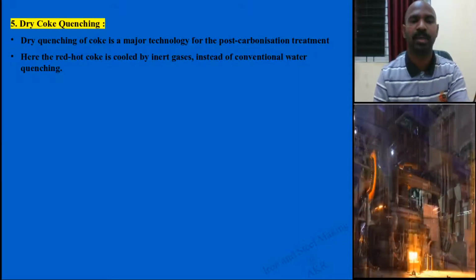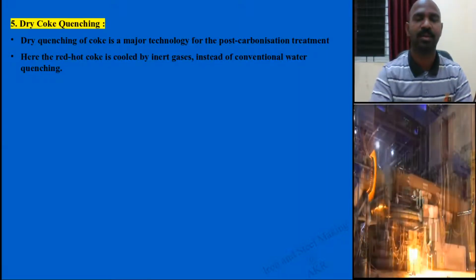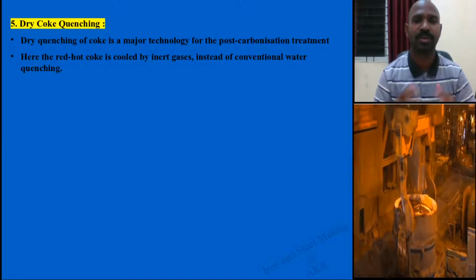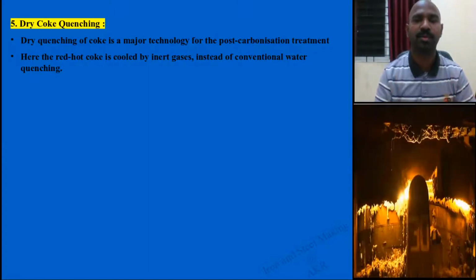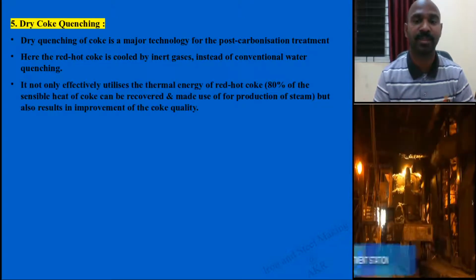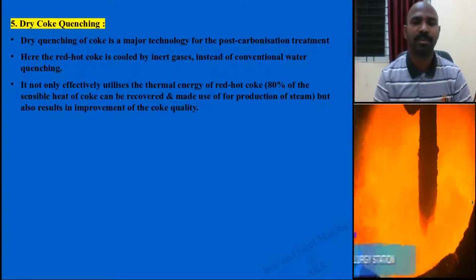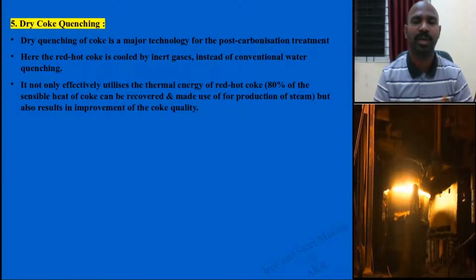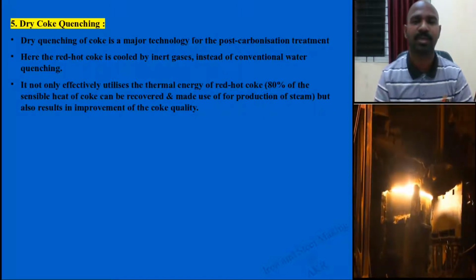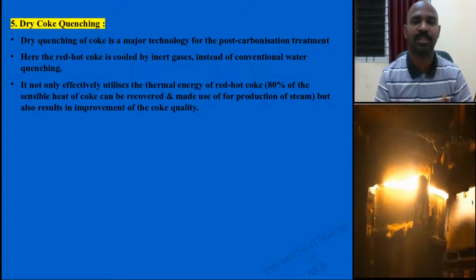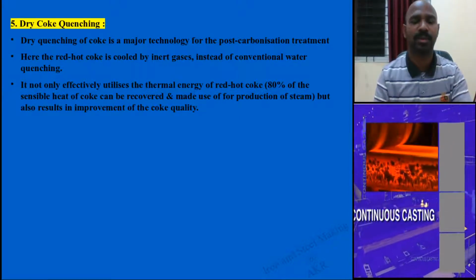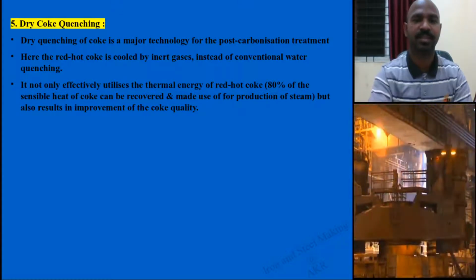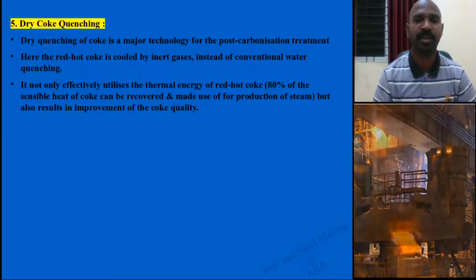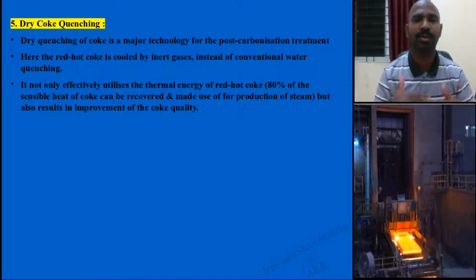Here you use inert gases. The coke is cooled by inert gases instead of water quenching. The red hot coke is taken and inert gases are used to cool it. The advantage of doing this is that not only does it effectively use the red hot thermal energy, it also improves the coke quality: fine size, large size, porosity, less porosity, reactivity, and strength will be improved if you include this step.